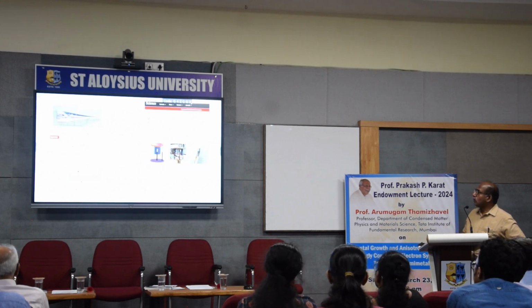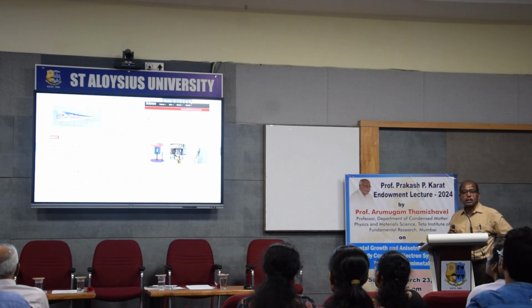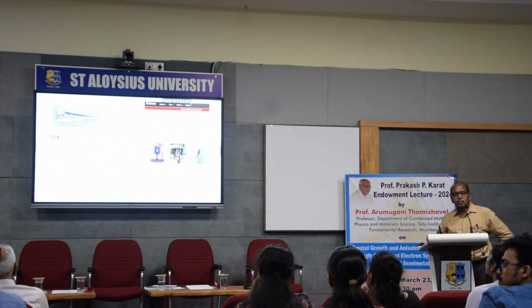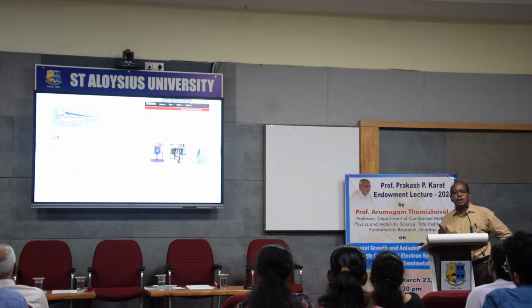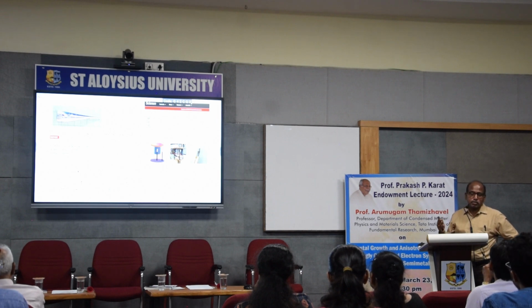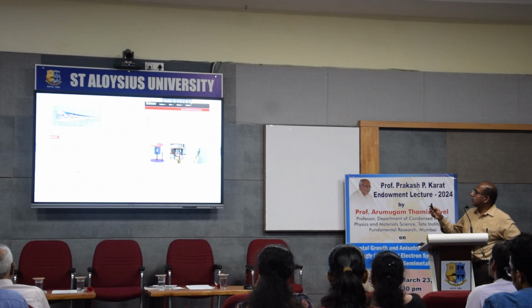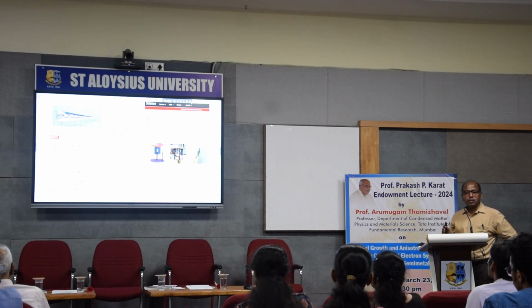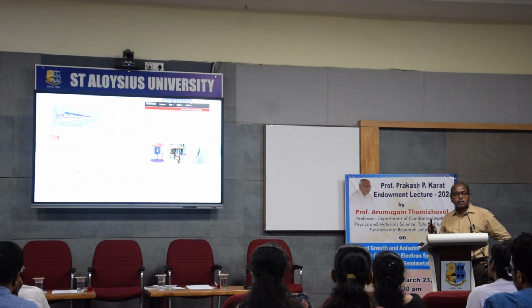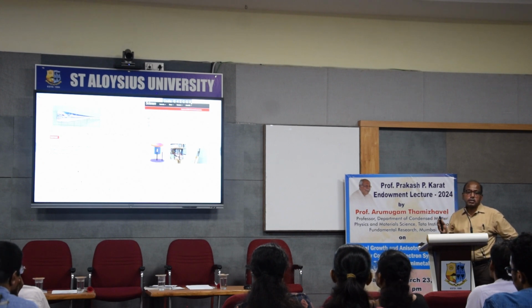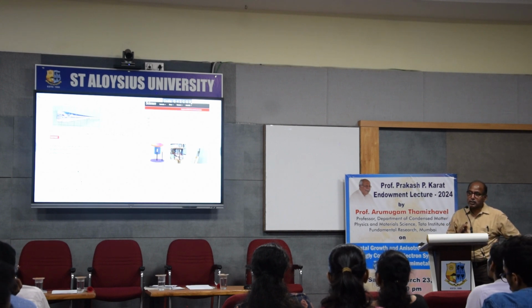Okay, so now we have grown this single crystal of bismuth in our lab, which is a high quality crystal. You know that bismuth melts at a very low temperature, around 270 degrees centigrade. But we have grown this crystal of bismuth by employing the Bridgman method, and we have studied the physical properties of this compound. One of my colleagues predicted that bismuth will show superconductivity at sufficiently low temperature. Sufficiently low temperature means very close to absolute zero. You know, absolute zero is not reachable. 0 Kelvin is not reachable.